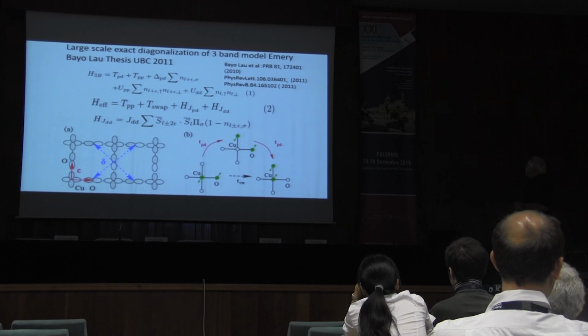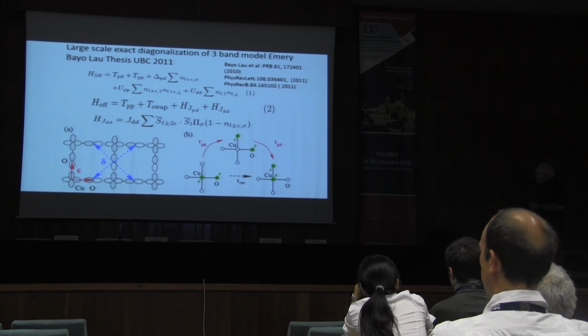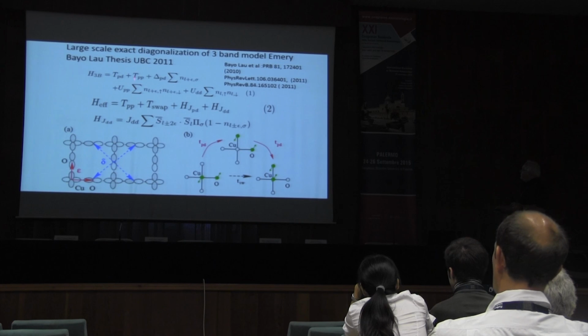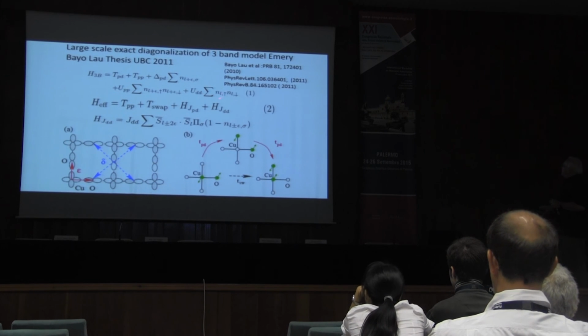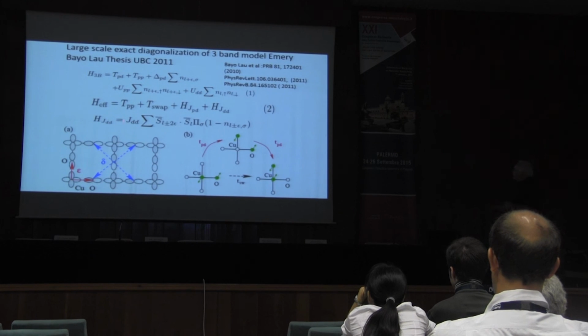And he, therefore, chose to do this calculation with a very, very big exact diagonalization type program. He used, indeed, the Hamiltonian in which you have both oxygen degrees of freedom and copper degrees of freedom, with U on oxygen and also U on coppers, and hopping integrals between them. The effect of the Hamiltonian that you could get if you make this U_dd very large is one that gives you a superexchange between the copper spins. They have a superexchange, antiferromagnetic exchange interaction, and it gives you an effective hopping integral between the oxygen.